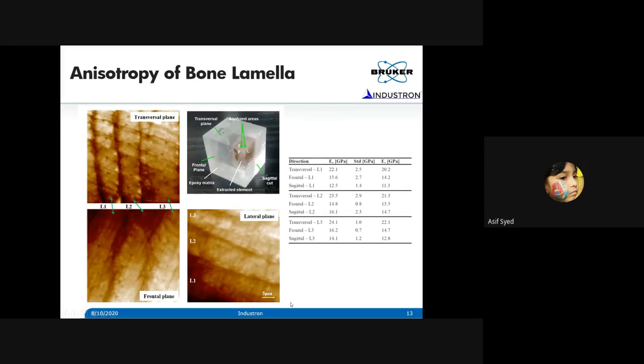So you can see this lamellar structure in the transverse plane. You can also see the indents being placed over here, the small indents over there. So this is L1, L2, L3, three lamellae where you can do the indents, both in the transversal plane as well as the frontal plane and the lateral plane, and you can get the modulus out of it.